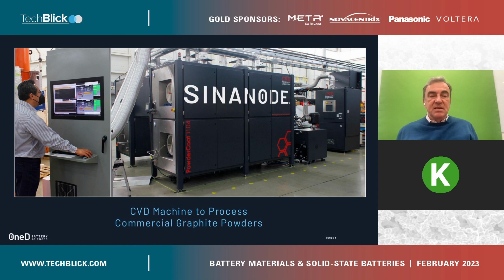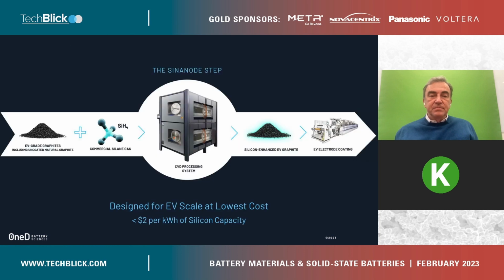Now, let me talk a little bit about the manufacturing process. On the left-hand side, you see our CTO, Yimin, and in the middle of the screen, you see the machine we use. This machine is very interesting because it's actually a machine that is used in the solar cell industry. If you go to, for example, Longi, which is the largest solar cell maker in China, there are hundreds of those machines. So we have a very low capex because we use something where normally you put solar cell wafers into the processing tube, but in our case, we put a reactor with the catalyzed graphite. And this specific machine is for the pilot production. It has 4 tubes, so it can do about 100 tons per year per machine, which is basically about 340 megawatt hours at 20% silicon, which is what our customer needs for pre-production of battery pack testing and qualification.